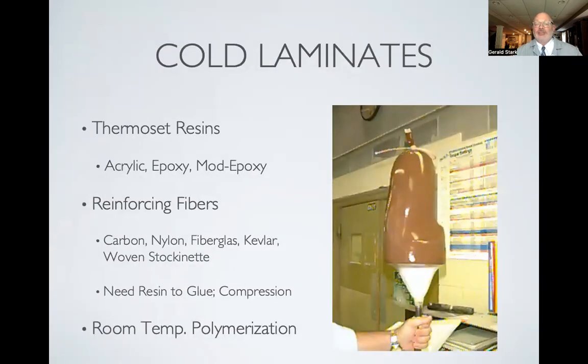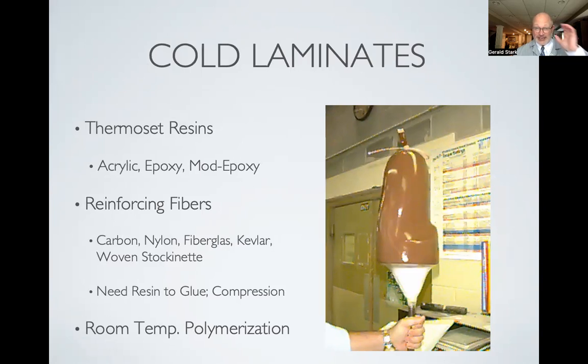So cold laminates are thermoset resin. Thermosetting resins can be epoxy. We used to think acrylic was a thermoplastic, but it's somewhere in between thermoset and thermoplastic. And then we use reinforcing fibers like carbon, nylon, fiberglass, Kevlar. Now these have to adhere. Nylon has a nice cuticle that really saturates well, fiberglass as well, but carbon does not, nor does Kevlar. So we have to figure out ways to glue these together, and that's what the resin does.